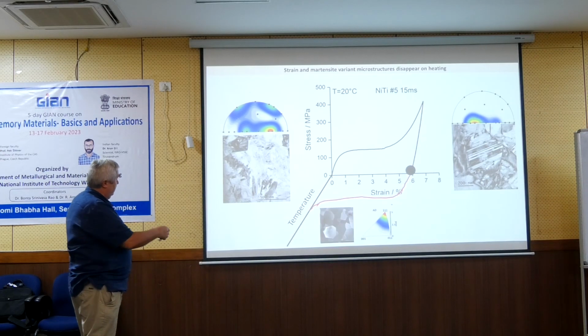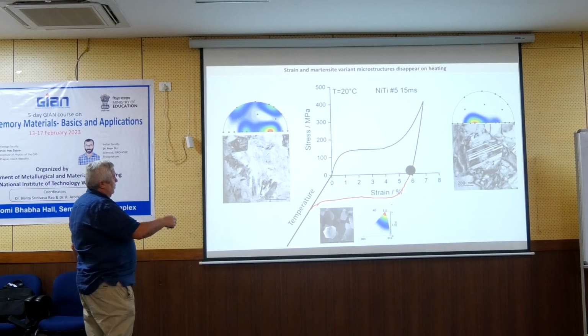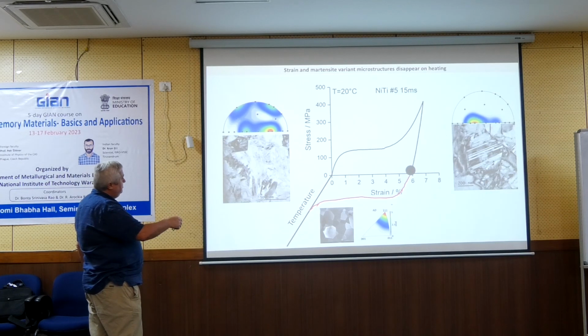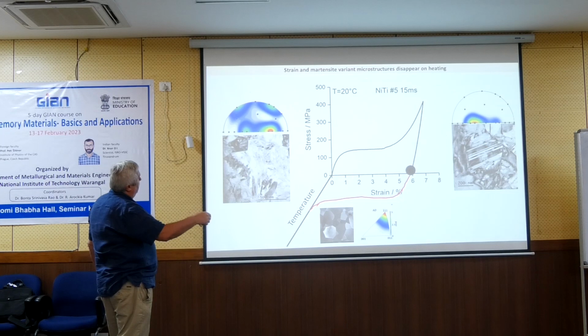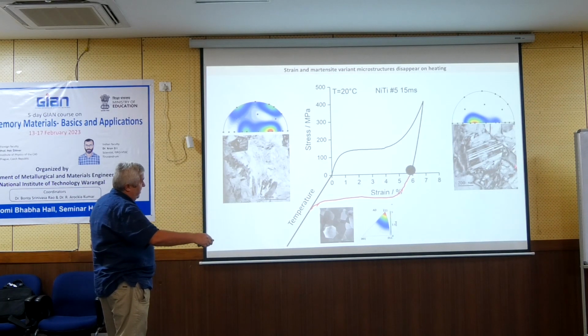Everything is on this figure. This is only for a reorientation. So I start with this kind of jungle with multivariant in grains. During the reorientation, it will change in such a way that there is a single laminate of 001 compound twins.